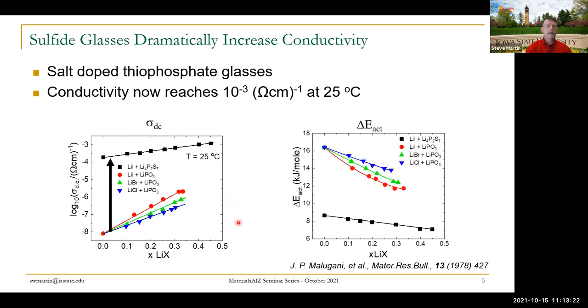And of course, why is that? Well, it's the binding energy of the larger sulfur anion. Sulfur is on the order of about 3.2 angstroms in diameter, around 1.5 for oxygen. So the charge density on that sulfur is much less. And also the polarizability of the sulfur anion is much larger. So the lithium ions can migrate through a sulfide network with much lower activation energy, a factor of two lower activation energy. And of course, because it's an Arrhenius dependence, that exponential dependence on activation energy dramatically lowers the resistance and you get this 10,000 fold increase in conductivity.